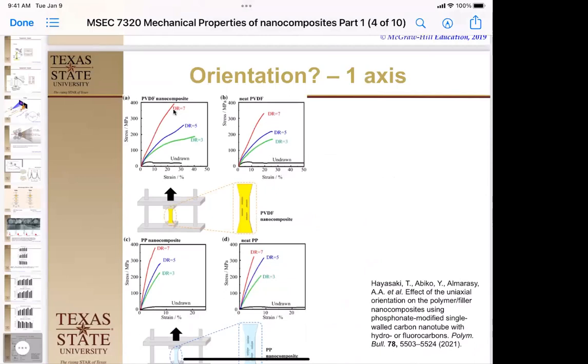Okay. So those may or may not have been ordered. Does ordering your nanomaterial help your flexural and/or compression modulus? Well, in an undrawn film of polyvinylidene difluoride, a nice piezoelectric polymer, it has very low modulus until you draw it out. But once you draw it out, at a ratio of 3 times, 5 times, and 7 times, our modulus goes up. So the neat polymer itself does improve its properties as we order. But if you look at the amount of improvement, having it as a nanocomposite is about 10% higher with a low loading of the nanocomposite. I don't remember the exact number, but I think it's around 3 to 5, 8%. And especially at 7, where it's drawn out 7 times, there's a much higher modulus.